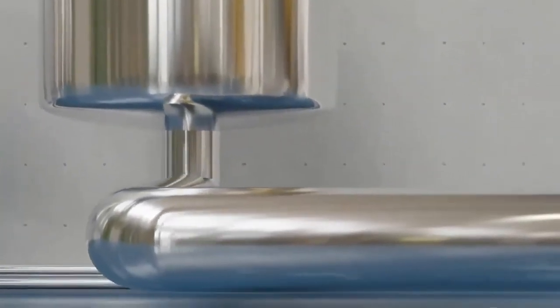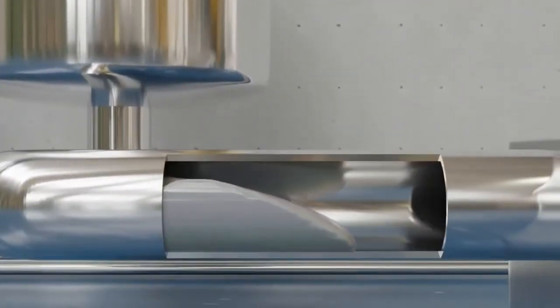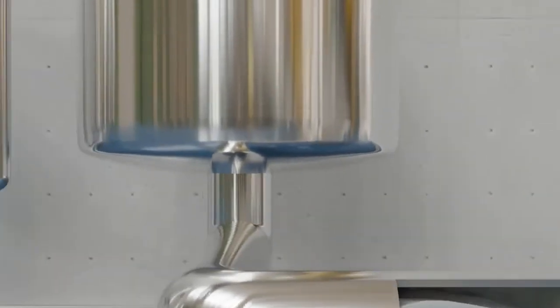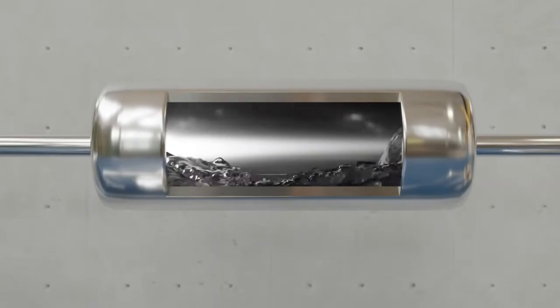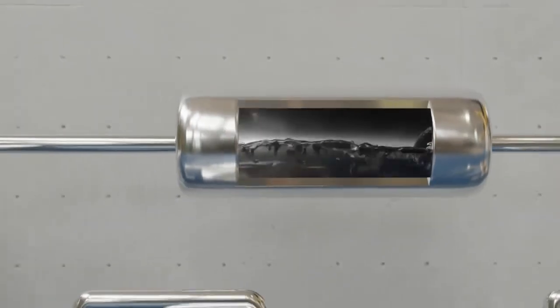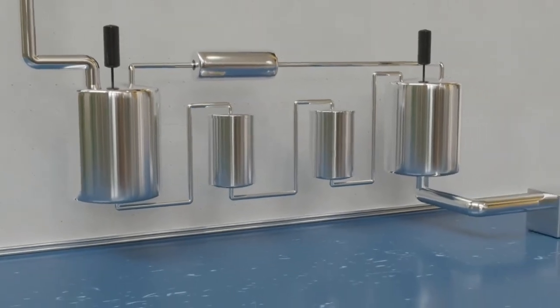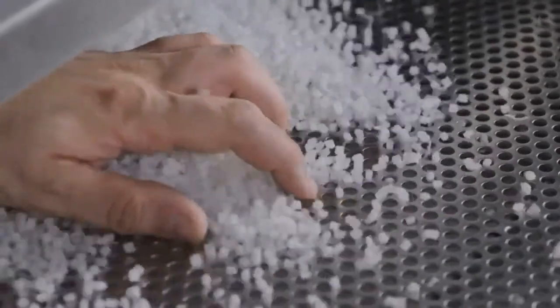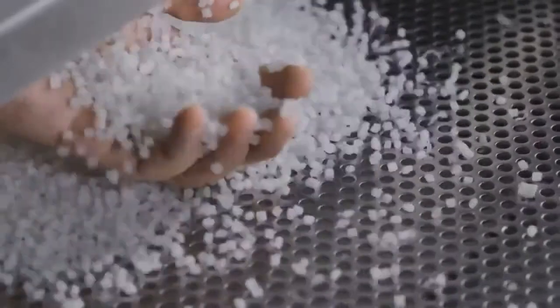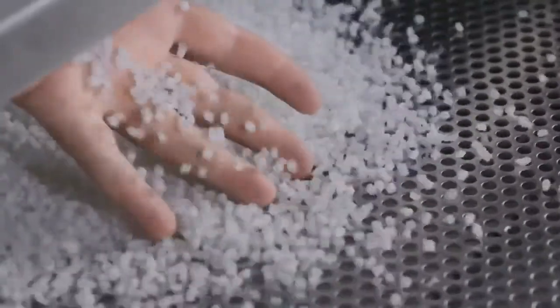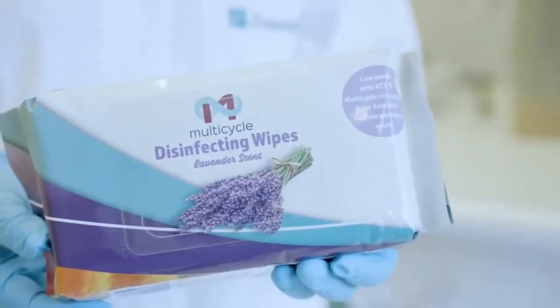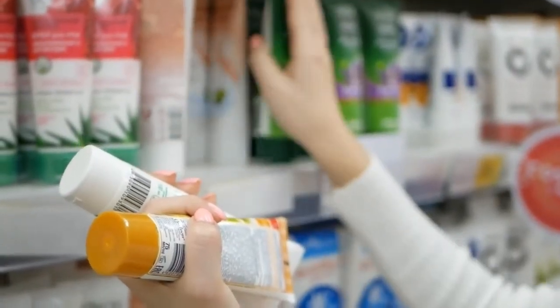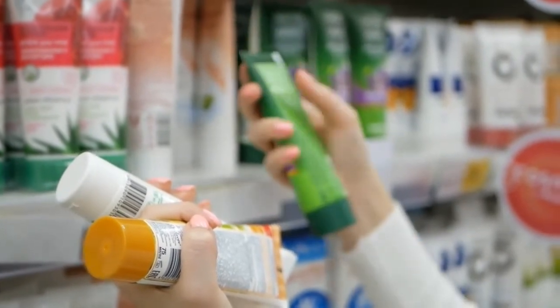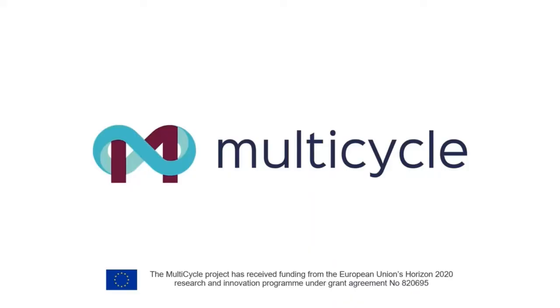The process allows recovery of near-virgin quality single polymer recyclates under moderate thermal conditions, using environmentally benign solvents, which are recovered in closed-loop fashion within the process for further cycles, and without recourse to chemical depolymerization. The recycled polymers obtained can then be reintroduced in truly circular fashion back into the value chains for manufacture of new generations of value-added, high-performance, plastic-based products. With all the concepts proved and invaluable experience gained on a representative, integrated pilot-scale industrial demonstration, the MultiCycle process is well set to take the next steps towards commercialization.